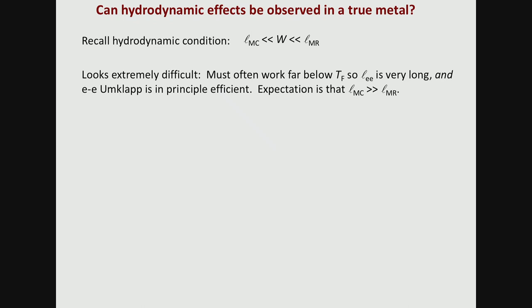So it's insane to try it on a full metal because the Fermi temperature will be very high, and that means that at your experimental temperatures, the electron-electron mean free path will be extremely long. Say in copper at 10 Kelvin, the electron-electron mean free path is centimeters. Whereas what you're always wanting is a mean free path of hundreds of nanometers.